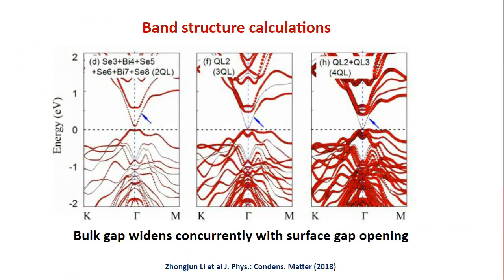Of course, these are again band structure data, like I was showing. Back to spaghetti lines, very complicated. This is obtained through DFT. This is the band structure shown by another group, and our data agrees with that. The light red lines are the surface states. You can see that when you go from 4 quintuple layers on the right to 2 quintuple layers, the surface states open up a gap, and the bulk bands move away from each other. I'm drawing this dashed line. That's the difference we are picking up. It's a small difference, about 0.2 to 0.3 eV, due to the finite size.